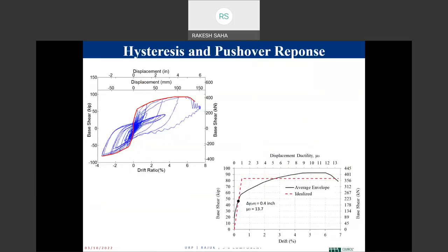Now, we tested this on a shake table. Again, to limit my presentation, I try to not have that many video clips here, but what's important, let's look at the figure on the upper left. You're looking at lateral force versus the drift ratio of the column. First of all, you notice that you are able to develop large forces with a large, relatively high ductility. The drift ratio was over 6%. We began to fracture some of the bars. The bars here were conventional steel bars. And if you look at the right side of the figure, I'm not sure if you can see my cursor, but in this area, that's where we began to fracture some of the bars. And of course, the capacity, the force, began to drop.